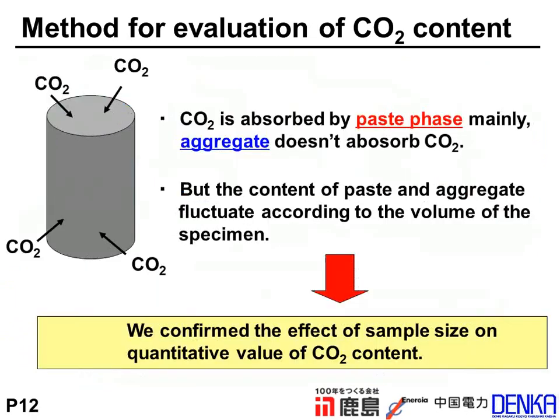But there is a little bit of a problem. In the concrete specimen, the carbon dioxide is absorbed mainly by the paste phase. The aggregate does not absorb carbon dioxide. But the content of paste and aggregate fluctuates according to the volume of the specimen. So we confirm the effect of the sample size on the quantitative value of carbon dioxide content.